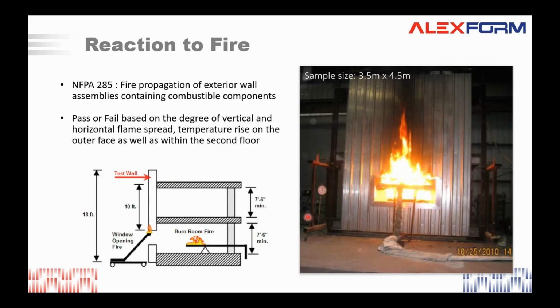What it wants to see is that this fire should not reach the second story internally, and this fire on the facade should not go above a certain level vertically or horizontally, should not spread too much. And the temperature rise on the outer face should also be within a certain limit. If you are within these limits, if there is no fire within the second floor, then you pass this test. This is a pass or fail criteria test. Now you see the test standard, that the sample size has grown a bit bigger, more representative of an actual condition, let's say, because here also the panel joint is affected.